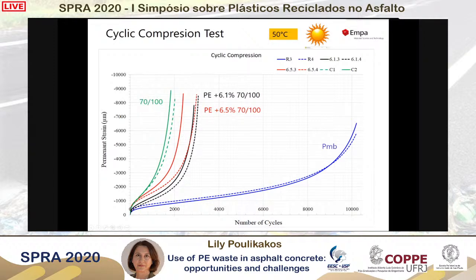So we were able to move the turning point a bit to the right, however, not enough to reach the polymer modified mixtures. So I think that so far, even though in the binder test we expected that the high temperature behavior would be comparable to PMB, we could not reach that when we saw the mixtures' performance. So at low temperature we came close, at high temperatures we did not. So the mixture needs to be more refined and adjusted.